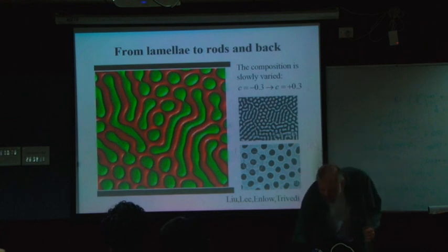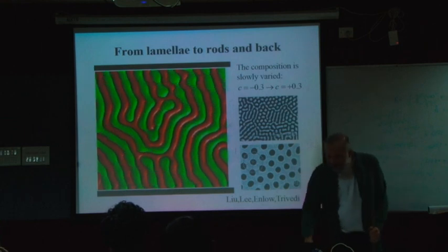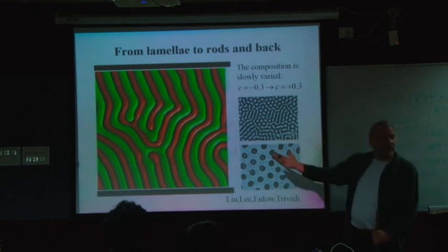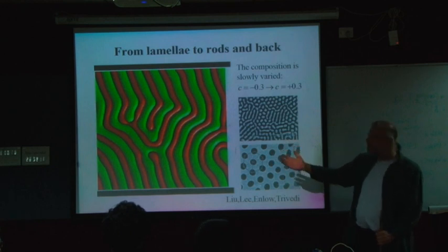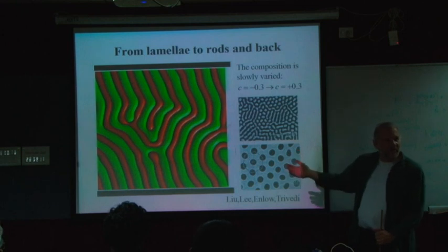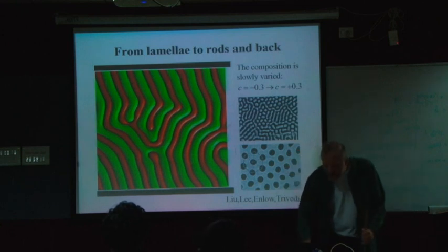And now something else also, if you look at the lamellar structure that forms after the reconnection here, you see that it's much more regular than the one that I got when I started from the random initial state. So visibly, the history of the transformation is important, and if you get a pattern out of a transition, it's going to be much more regular than if I start from random initial condition.